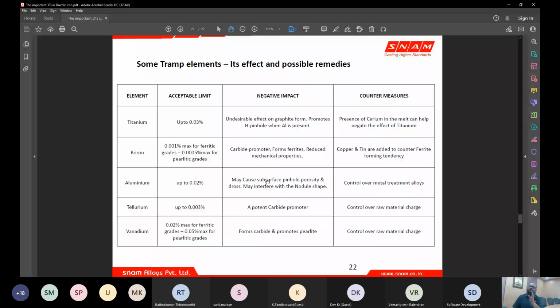Say for example, titanium: the generally acceptable limit in foundries for ductile iron should be 0.03%, because titanium generally forms titanium carbides, and it can lead to hydrogen pinholes when aluminum is present. So here we can see a combination effect. When titanium goes high, and you already have aluminum available in your liquid metal within the controlled level, titanium plus aluminum can lead to increased hydrogen porosity. So to some extent, cerium additions can be done to negate titanium, or you can avoid titanium-rich scrap material or returns material in your liquid metal, such that your titanium levels are controlled. Boron, again: in ferritic grades it has a different control, and in pearlitic grades it has a different control.